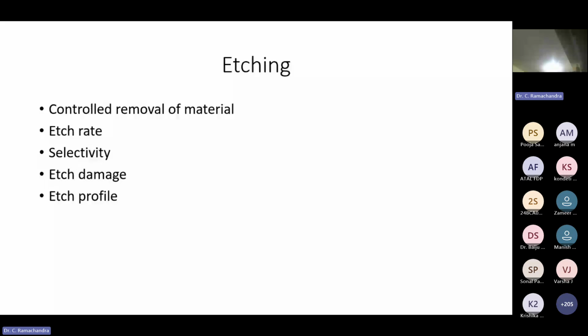Then etch damage. Today, most of the etching is done by plasma. Plasma means it is an energetic ion beam. This ion beam should not add impurities, should not leave ions trapped in the device and create circuit problems later on. Etch damage, what tolerance do we have? And etch profile. In some applications, I am going to show you, we need deep etch with 90°. In some applications, we need tapered etch. So how do you control the etch profile? These are some of the important challenges and requirements.